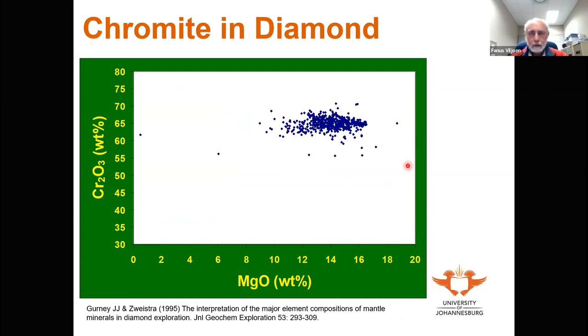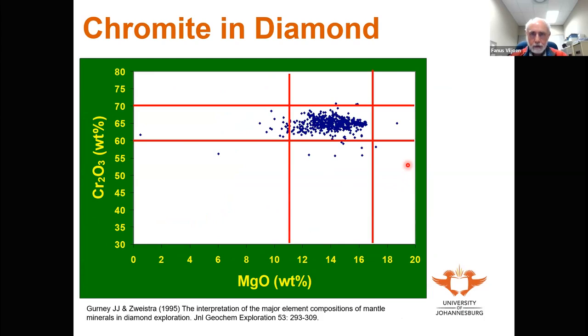That is another very common inclusion variety in diamonds. And if you look at their chrome and magnesium contents, you find that they have high chrome, between about 60 and 70 weight% chrome, and on the order of about 11 weight% magnesium to about 17% magnesium. And again, this forms a prospecting tool because you see an abundance of chromites in diamonds, and those diamonds are peridotitic diamonds because this is a peridotitic mineral, because it has this high chrome content and this high magnesium content. If you start seeing these chromites in your prospecting, there's a possibility that these chromites could be from diamond-bearing kimberlites.